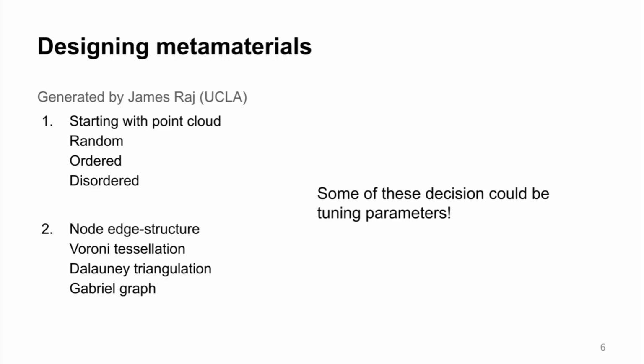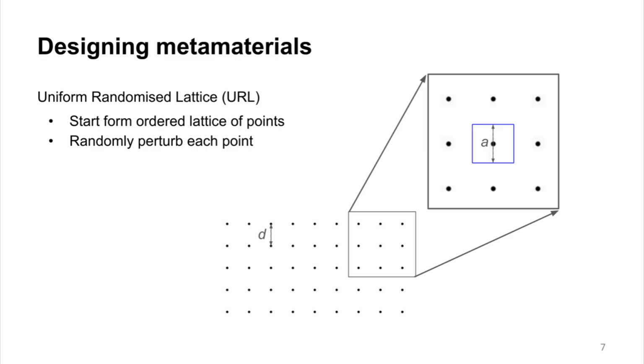The starting point distribution could be random, it could be ordered, or it could be a known hyperuniform distribution. There are various protocols that exist that I will explain in upcoming slides, and those include Voronoi tessellation, Delaunay triangulation, or Gabriel graph. There is a way of generating a point cloud called the uniform randomized lattice, and in that we start with a uniform ordered distribution of points, and since our ordered distribution of points is known to be hyperuniform, it is also known that uncorrelated uniform perturbation of these points also turns out to be hyperuniform, and we could control the amount of disorder by controlling the parameter A, which defines the size of the window.